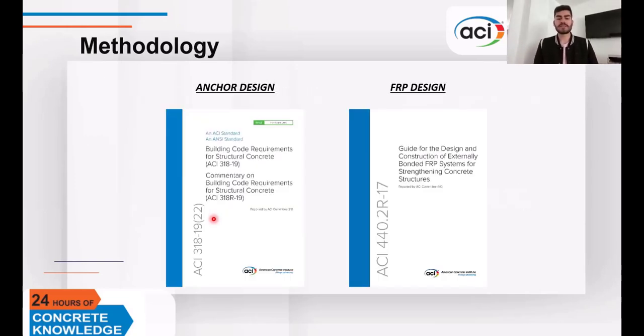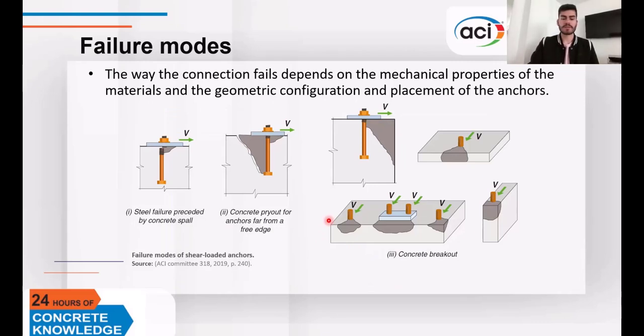Now, everything related to anchor design was done according to the guidelines in ACI 318, and everything that involved FRP considered ACI 440. Now, these are the three failure modes of shear-loaded anchors as represented in ACI 318. Concrete breakout on the right is the most common when anchors are close to the edge, as I mentioned before. On the center, we have concrete pry-out.